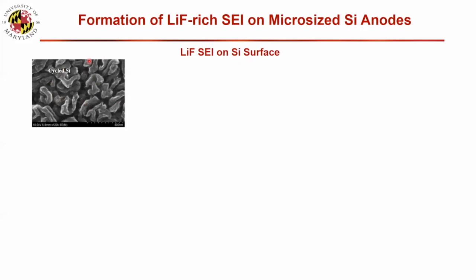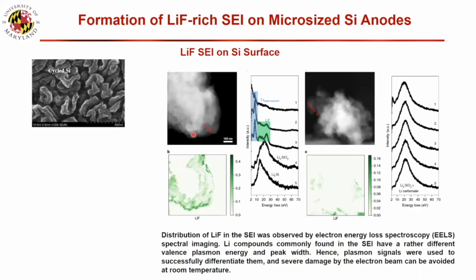So this is after many cycles. You will see the silicon at the beginning is a particle. Right now it's like a fiber because they have a crack, but they are not separated by electrolytes as yet. And then we check if the surface really has lithium fluoride or not. This is a silicon particle, and then we use EELS to map the lithium fluoride. We really see the lithium fluoride covered on the surface.